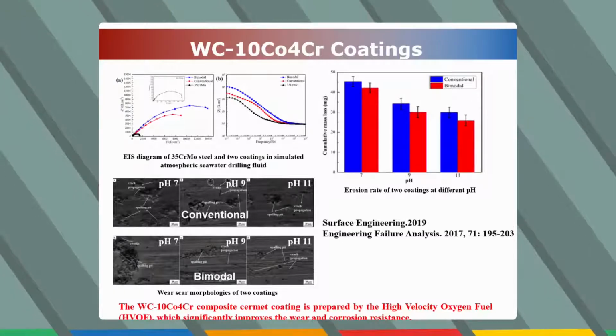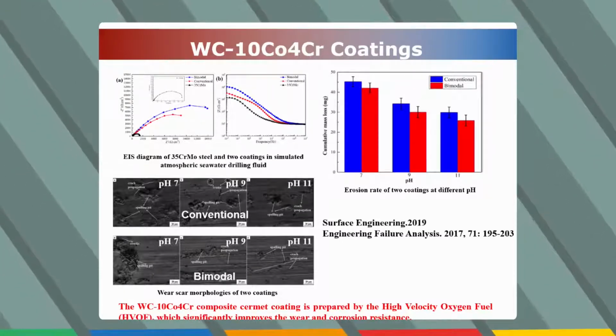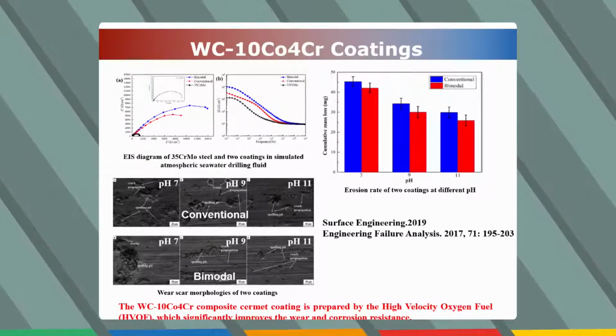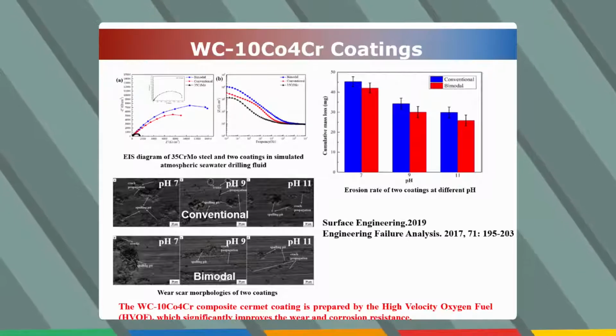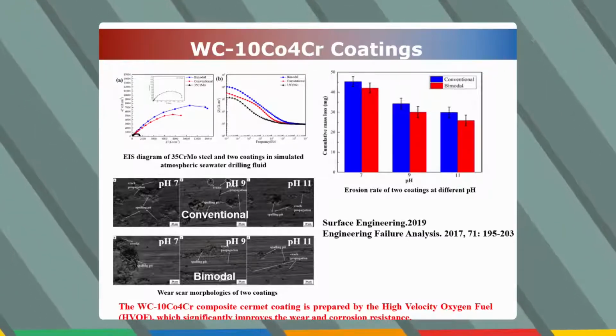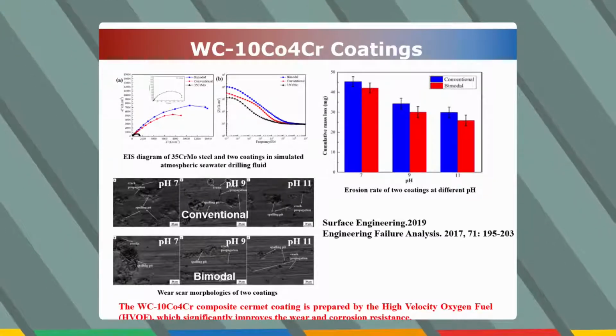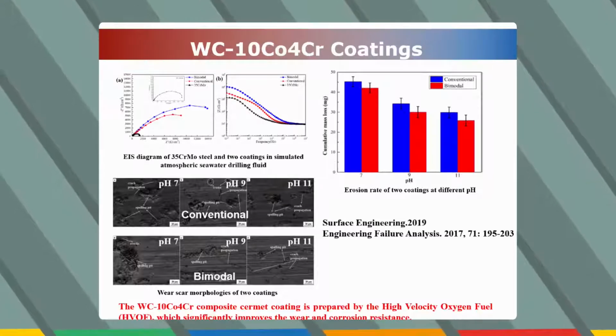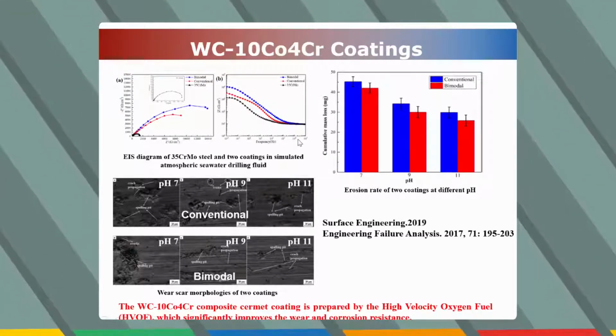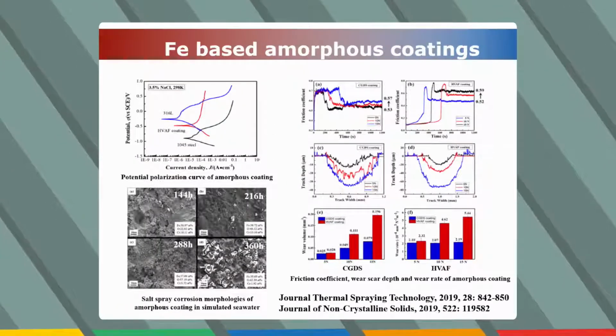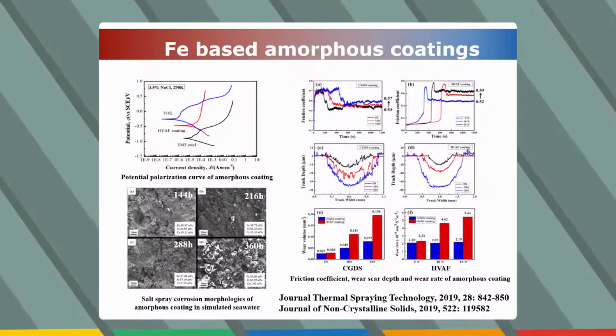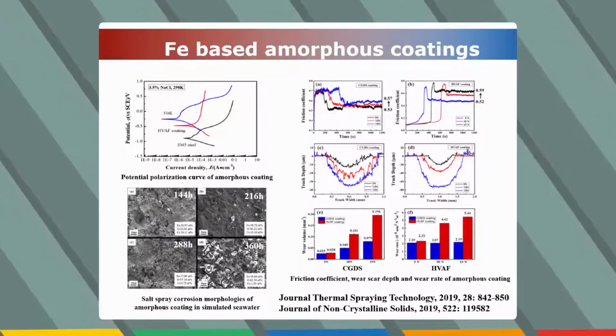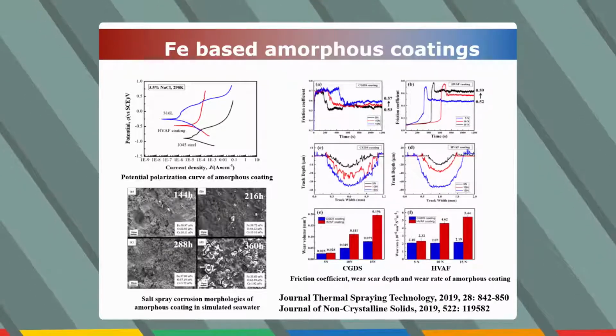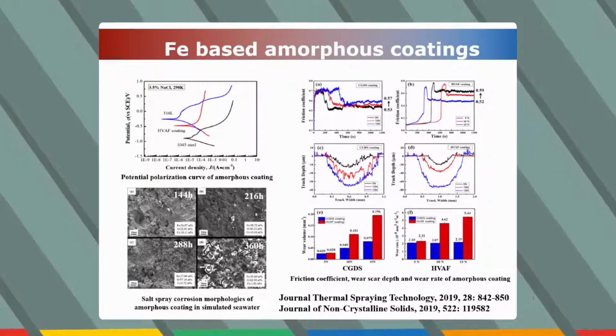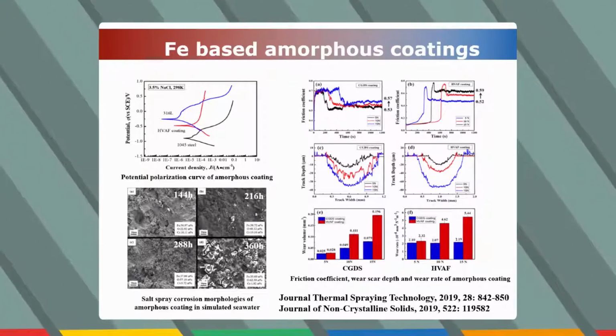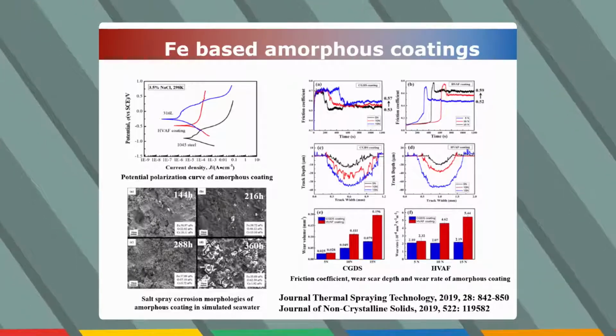This slide shows the tungsten carbide cobalt chromium composite cermet coating prepared by high velocity oxygen fuel spraying, which significantly improves the wear and corrosion resistance of vulnerable parts of drilling equipment under complex working conditions. The iron-based amorphous coating was provided by cold spraying and thermal spraying respectively, which improved the surface mechanical properties and corrosion resistance of workable parts of drilling equipment.